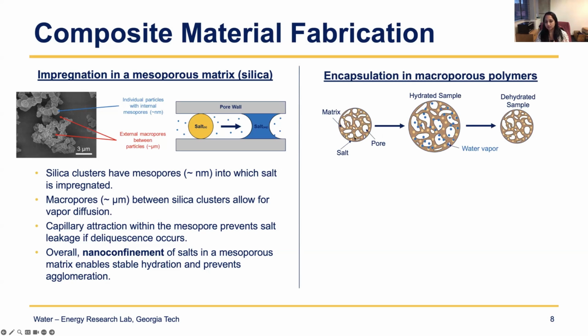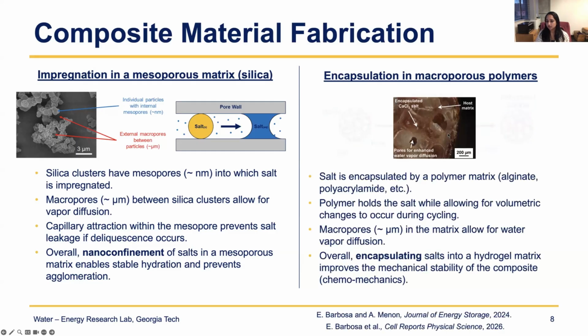So if you have a polymer matrix or a hydrogel, you essentially put the salt within the hydrogel matrix, and the hydrogel has mechanical flexibility or elasticity. So as the salt hydrates, it undergoes volumetric expansion, and the hydrogel expands to allow the hydration. And then when you dehydrate, you can contract, and the salt has that space to move as it expands and contracts. And there are also pores within the matrix to allow for the water vapor to transport and allow the chemical reaction to occur. This is what it really looks like.